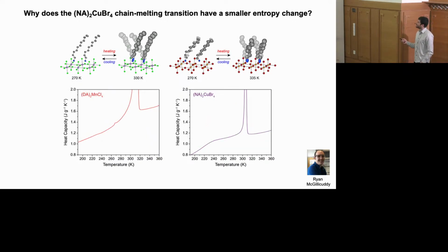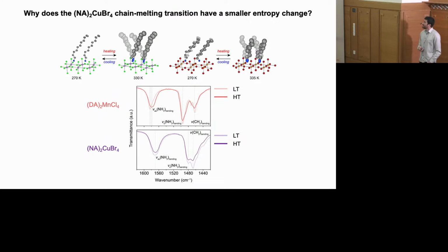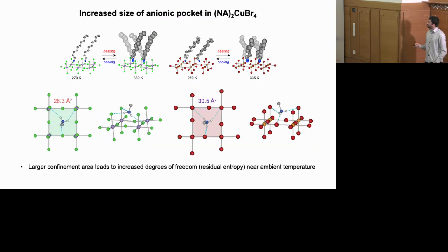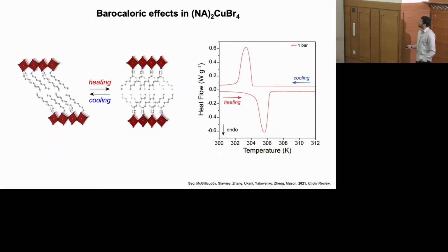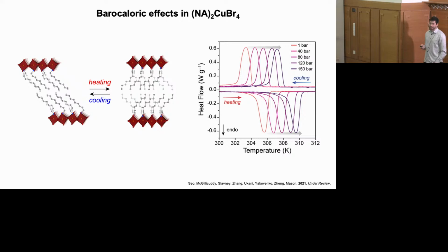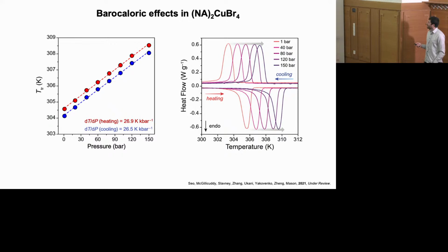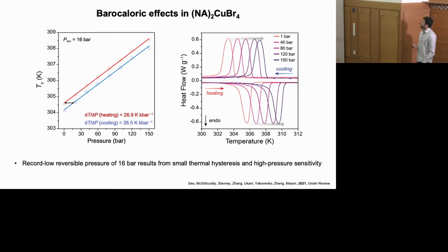And so we can see this in the heat capacity of this material, where we see a broad feature that's consistent with gradual activation of molecular motion in the low temperature phase of this material. And we also see this in infrared spectroscopy as well. And as I mentioned, we think this is due to the roughly 15 to 20% larger cavity size of this bromide anion. So this material has a similar kind of sensitivity to pressure as the first compound I described, actually a little bit higher sensitivity to pressure.